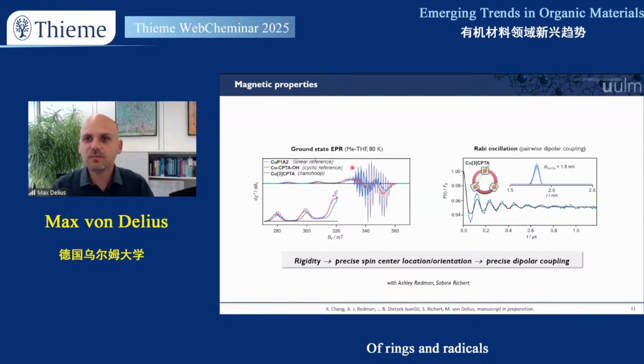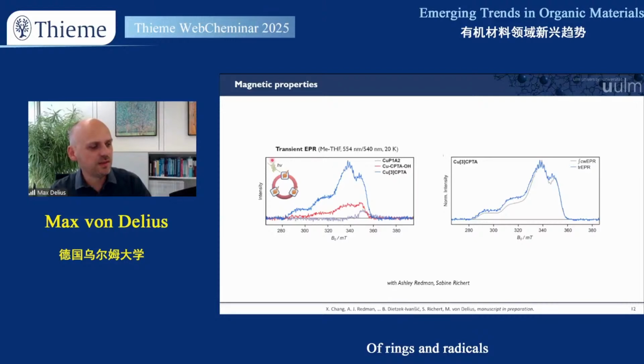So the really interesting results began when Sabine studied now the dipolar coupling between spin centers. And she saw that only in the nanohoop is she able to record this really well-behaved Rabi oscillation, which actually allows you to measure the distance between the copper centers, which basically by shining light on the molecule.